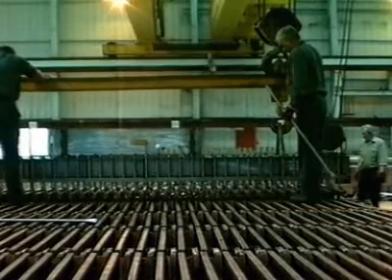Once a week, the cathodes, with a 6 mm thick coating of copper on each side, are removed from the cells. The deposited copper is separated from the cathodes by flexing them and stripping the copper away with knives. Plastic strips prevent copper being deposited on the edges of the cathodes. The steel cathodes are then reused.